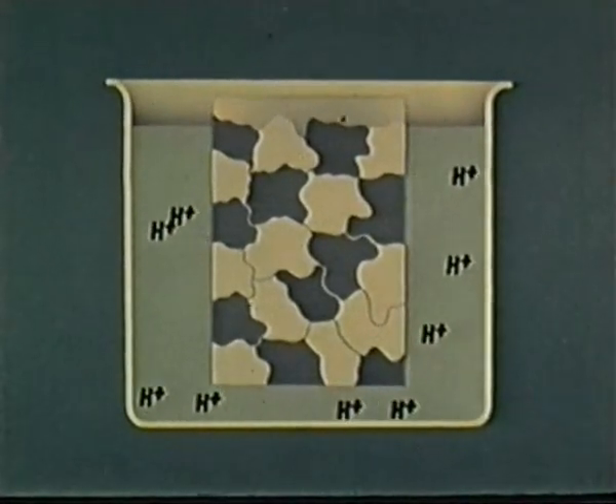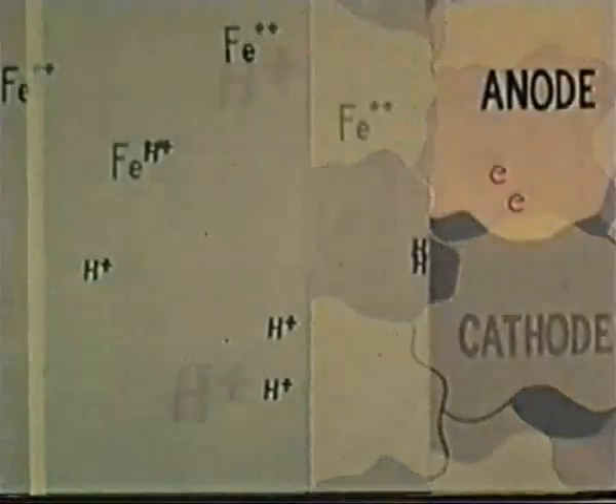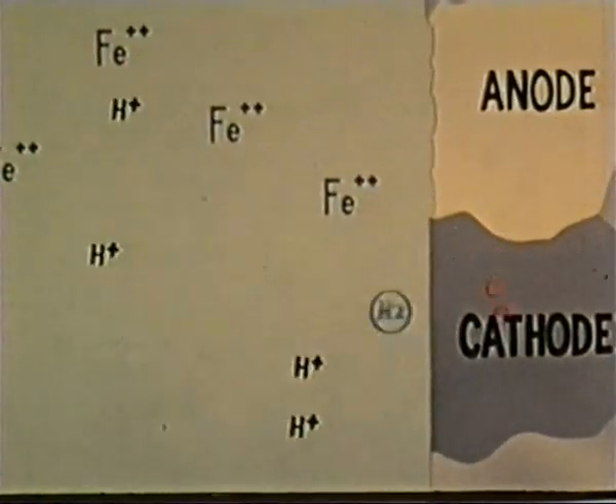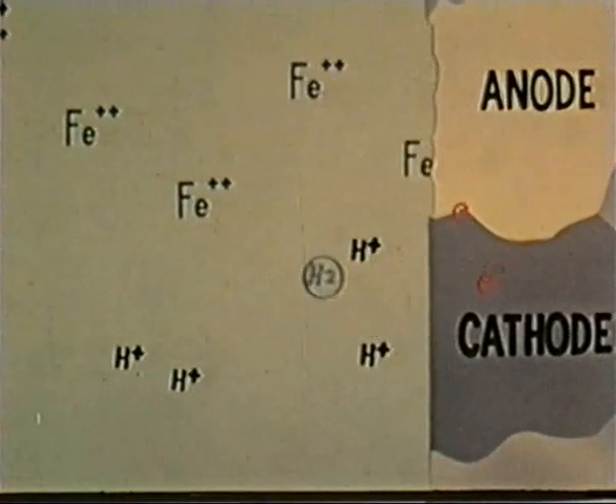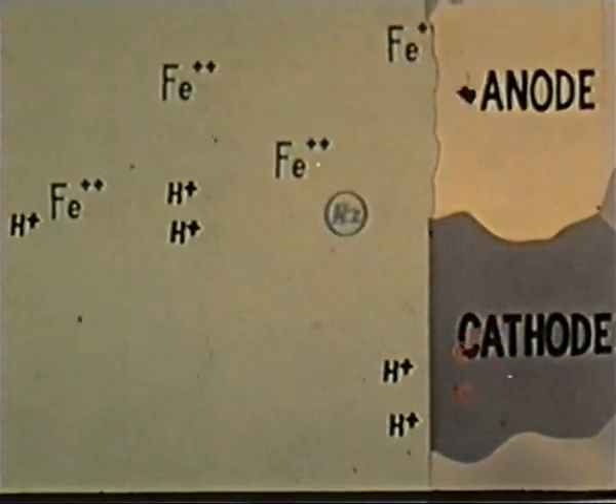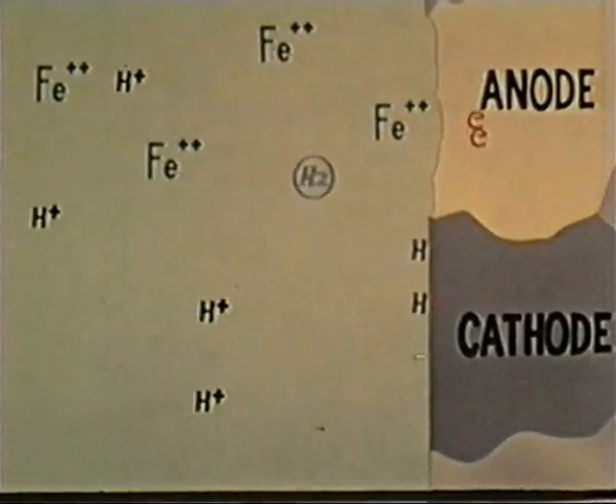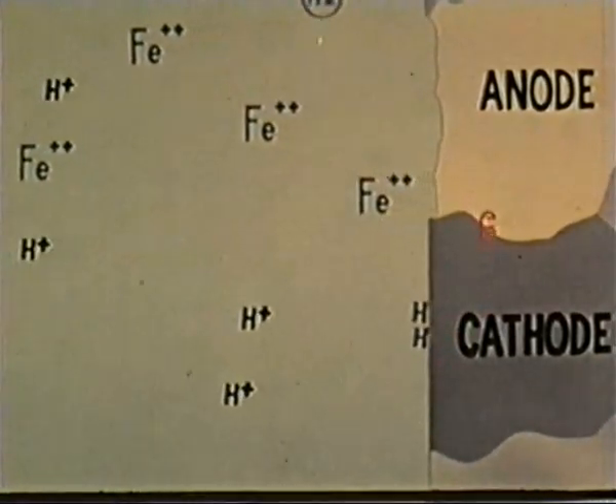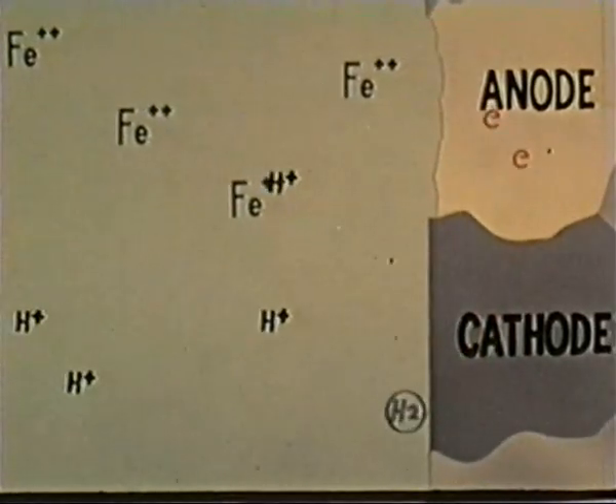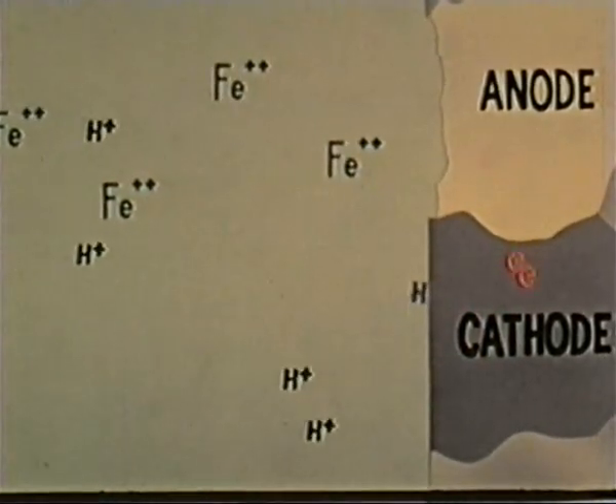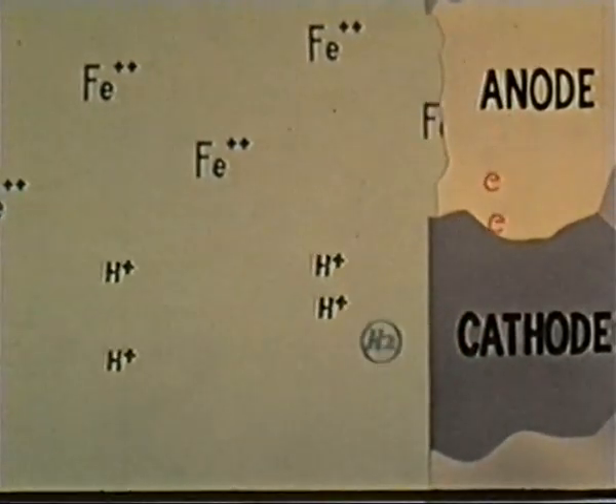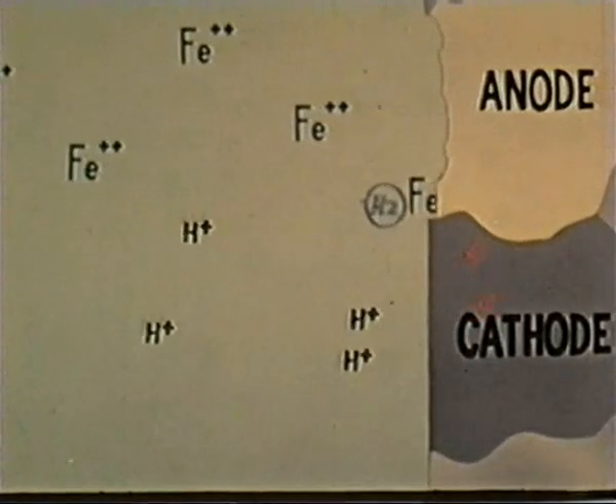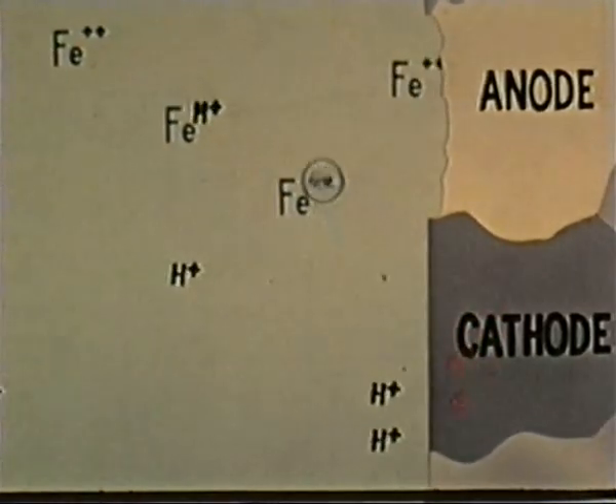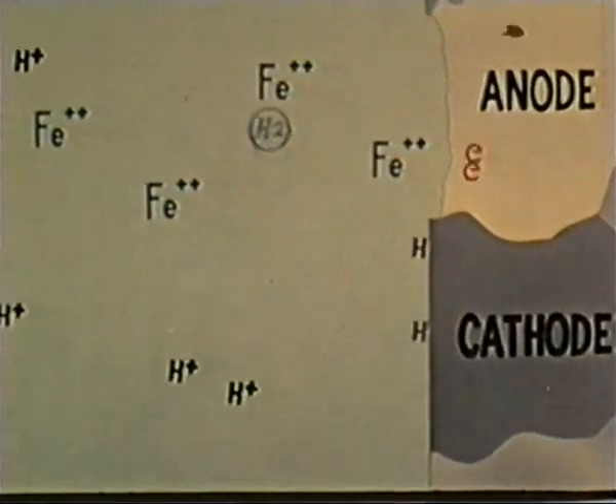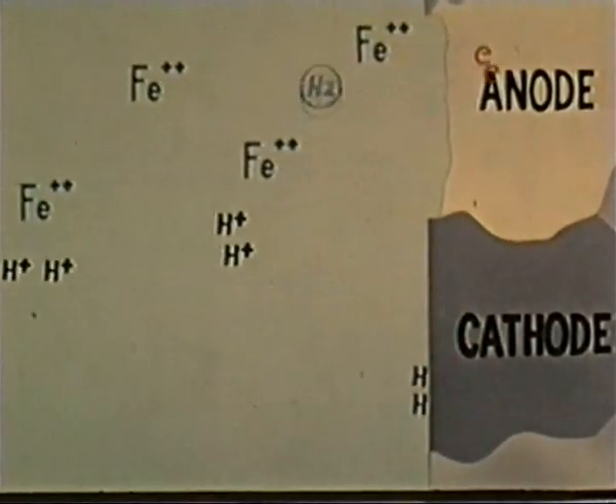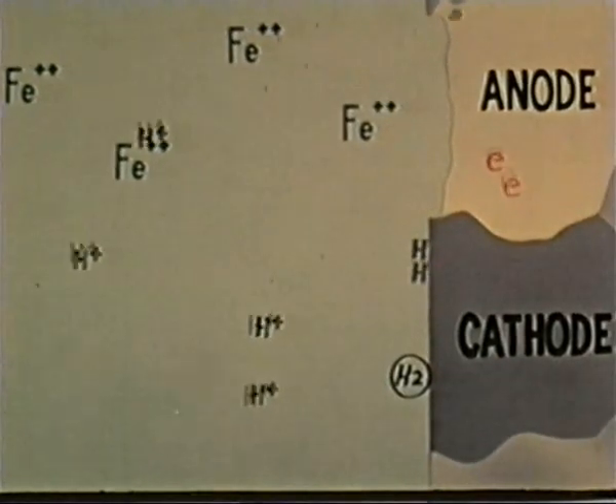If we could see just one anode and one cathode in a giant view, we would see electrons released by the formation of each ferrous ion flowing through the metal from the anode to the cathode, where they meet the hydrogen ions in solution, which act as electron acceptors at the cathode surface. One electron is accepted in the discharge of one hydrogen ion. The hydrogen then appears as hydrogen gas coating the metal surface. As this process continues, oxidation and corrosion of iron occurs at the anodes, and plating out of hydrogen occurs at the cathodes. This formation of hydrogen molecules and the evolution of hydrogen gas are the principal reactions in corrosion by acids.